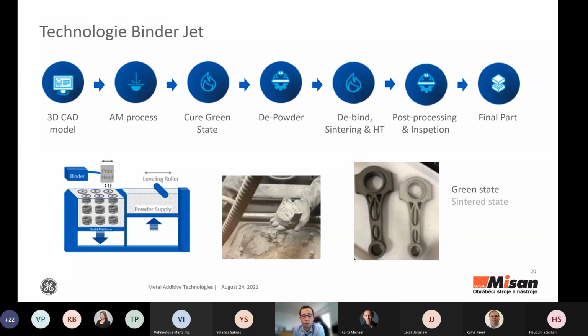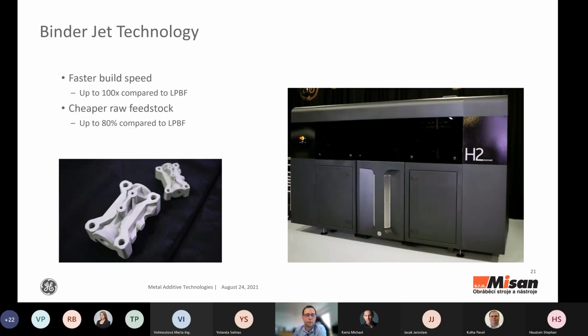As you can see in the picture on the right, there is a certain disadvantage of this technology, and that's the shrinkage during sintering, which can be up to 30%. But the advantage here is that the speed of build is 100 times faster than with the most frequent laser powder bed fusion.